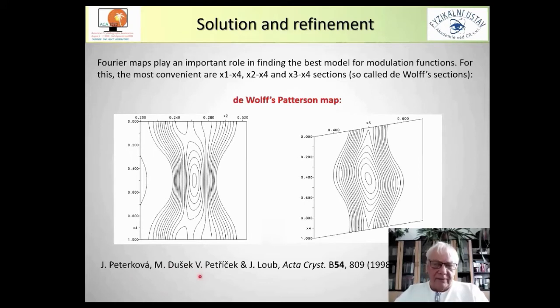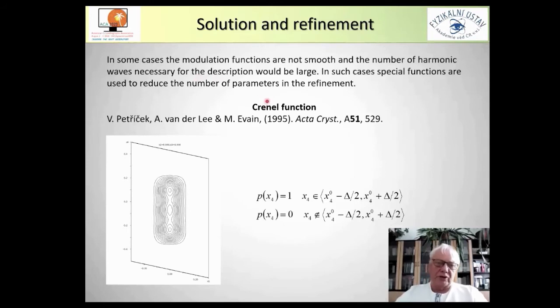The sections can also be used to correct the final model by using a difference Fourier map. From these differences we can conclude how many harmonics we need and whether we also need modulation of ADP parameters. In some cases, the modulation functions are not smooth, and the number of harmonic waves necessary to describe such a function would be very large. For such cases, a special function can be used to reduce the number of parameters in a refinement and to make a more realistic model.